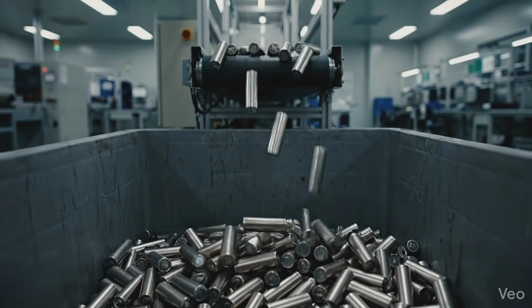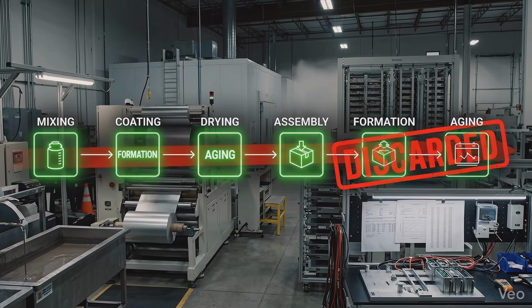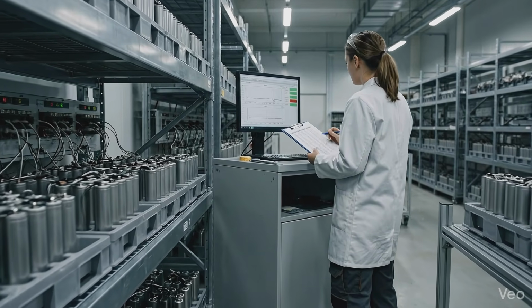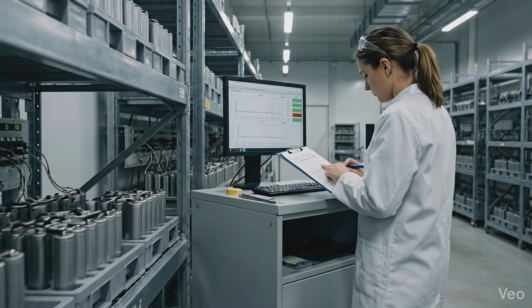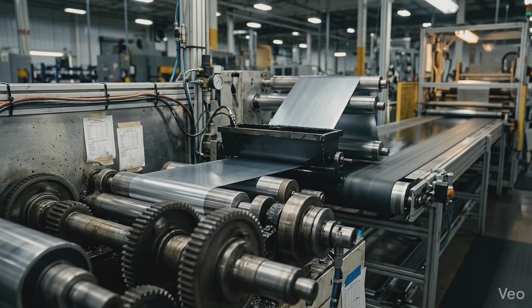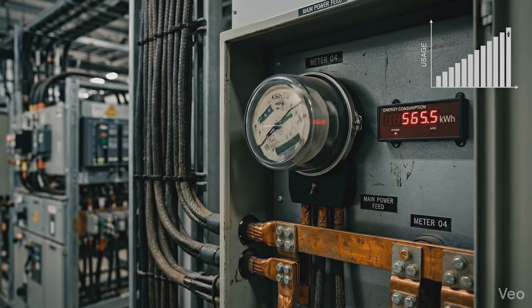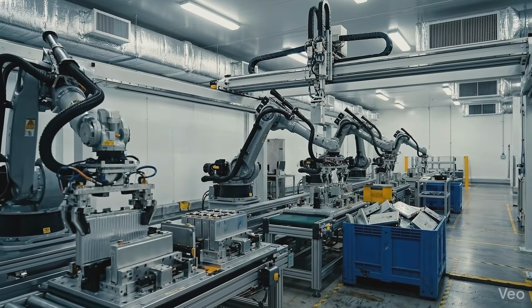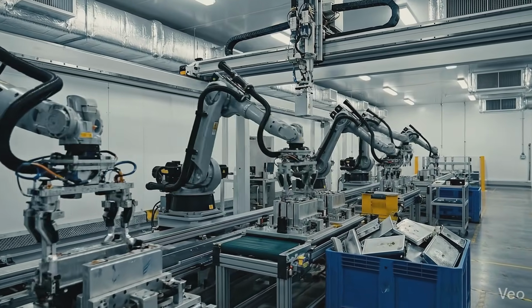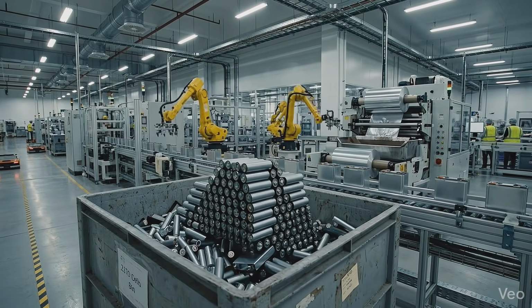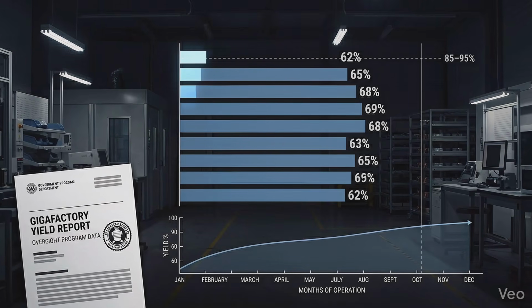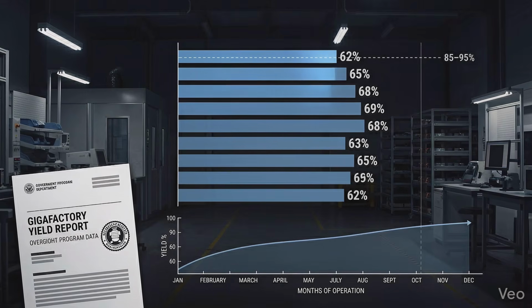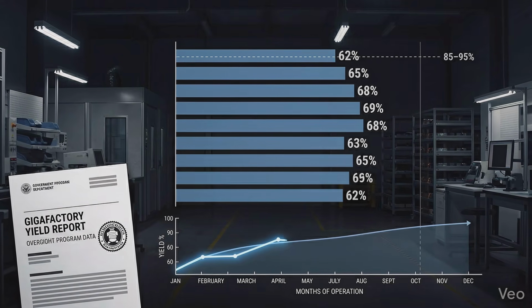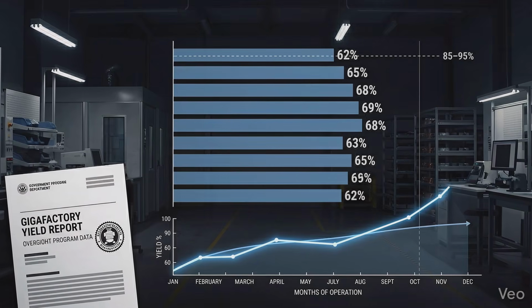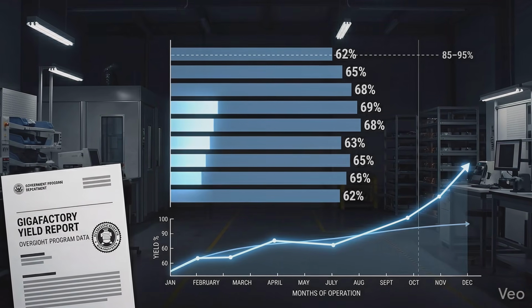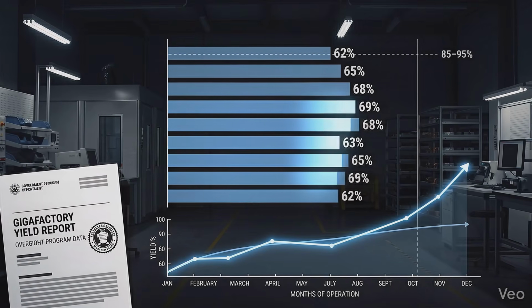The cells are scrapped. Every percentage point of yield below target represents cells that were mixed, coated, dried, assembled, formed, and aged, and then discarded. The machines ran, the energy was spent, the robots moved, and the cells still failed. This is why early-stage gigafactories, according to industry analysis and DOE program reporting, often operate at 60 to 70% yield during ramp-up phases, and why closing that gap to the 85 to 95% yield of a mature facility can take 12 months or longer of continuous process optimization.